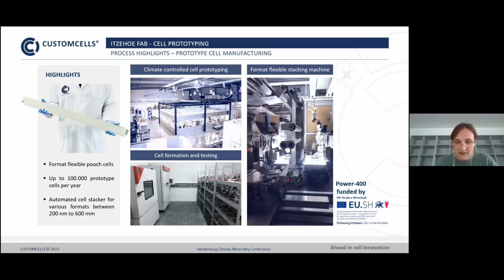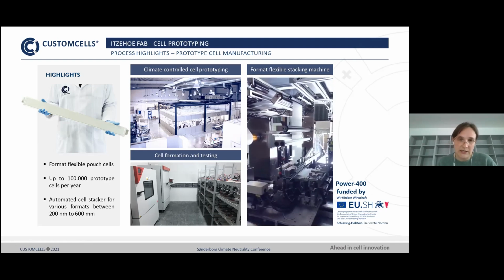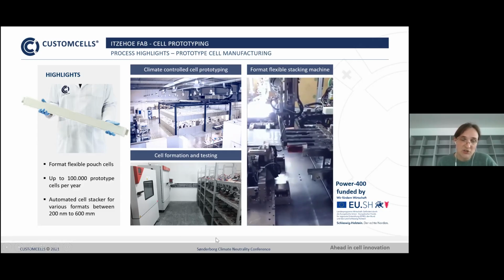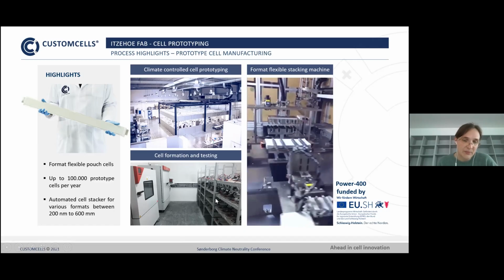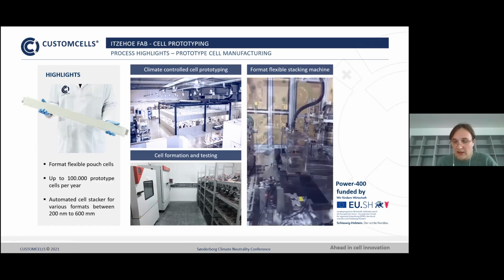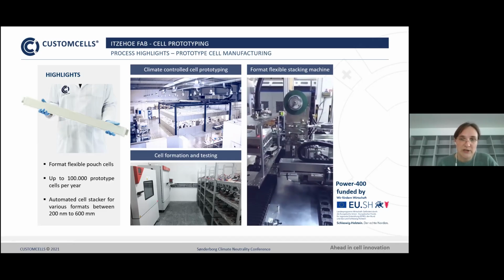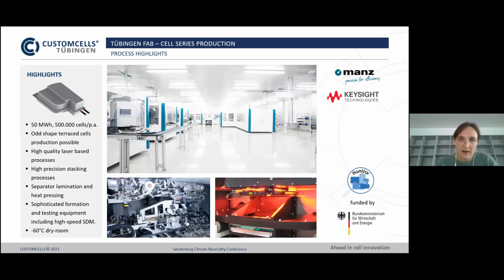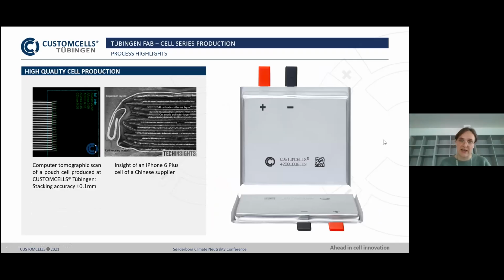In most cases, this is due to the salt that is inside the electrolyte. After the electrolyte filling, the formation starts, where the cell is first charged and discharged. Here the SEI is formed, and then the cell is more or less finished. In our production site in Tübingen, we have a fully automated process where we can build up high precision cells. This is an example cell, and there you see on the left side the high precision stacking in comparison to a commercially available cell that is much less precise in stacking. And this also helps to gain higher energy density, because you can have more space filled with electrode and don't need to have that much of a safety margin here.